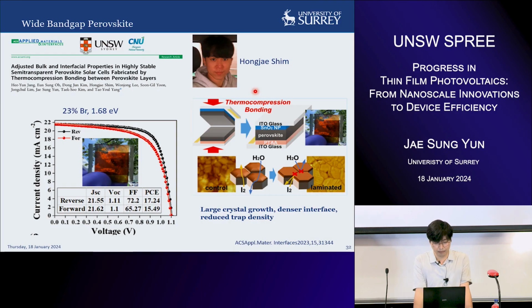My other student, Hong Jae, mainly works on nanoscale characterization, and we have collaborated with Chungnam National University. They were able to form a very nice wide-bandgap perovskite using a thermal compression bonding method. What they did is they made two perovskites separately, and they bonded the perovskites by applying pressure with temperature. This method will eventually make a very good bond between the materials, and we'll have a transparent perovskite, because you can have two glass substrates and just bond them together. They achieved around 17%, but there's a bit of hysteresis, which we think means there are still a lot of defects in the bulk.